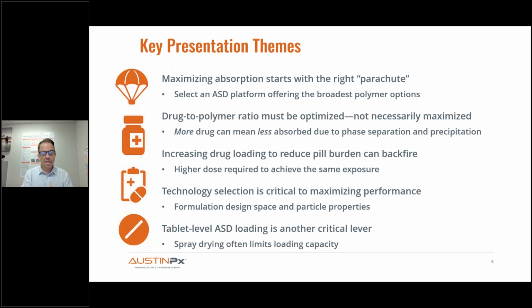performance. So technology really determines your formulation design space, which excipients you can use to formulate the product, and also, often overlooked but now becoming more and more apparent in the literature, is how particle properties are impacting performance, and there'll be a lot more on this later. Finally, tablet level ASD loading is a critical lever. It's not just about drug loading in the ASD, it's also about how much ASD you can load in a final tablet while maintaining target tensile strength and disintegration properties.